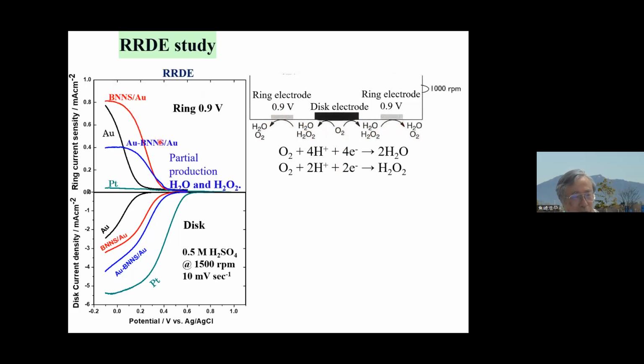In the case of gold, this is the disk electrode. The disk current means the reduction of oxygen, and the ring current shows the hydrogen peroxide oxidation. So in the case of gold, there is a lot of hydrogen peroxide. On the other hand, the other limit is platinum. Platinum has a very large disk current because of the very high catalytic activity, and the ring current is very small, because in the case of platinum, oxygen is reduced to water. Water is not oxidized at this potential, so there's no current here. So this ring current to disk current ratio is very important.